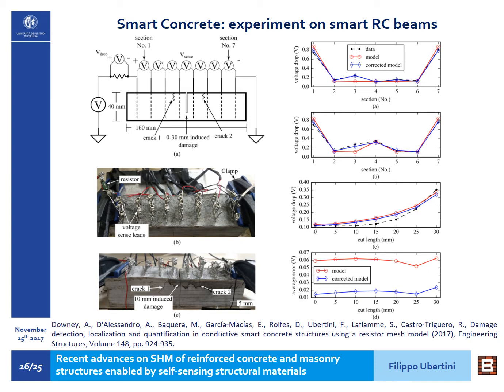Clearly, when we apply a damage, as we see in the third diagram, we have a change in a voltage drop, and in particular when there is a damage in a section between 2 electrodes, we have a local increase in electrical resistance, which means for a constant electrical current, an increase in the voltage drop across the 2 electrodes. And this increase grows very nicely with the length of a cut, for instance, when artificially damaging the beam. So we can conclude that this approach of locally measuring the electrical resistance of the material, or the voltage drop under an external voltage input, is feasible for detecting and locating a damage.